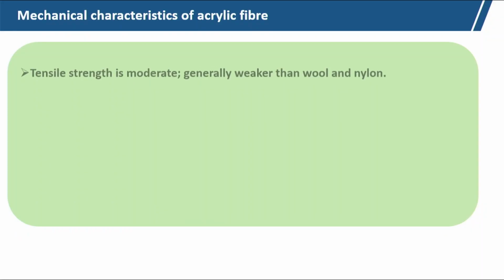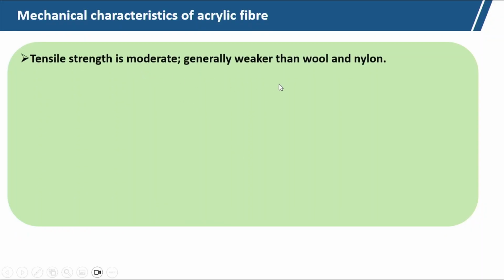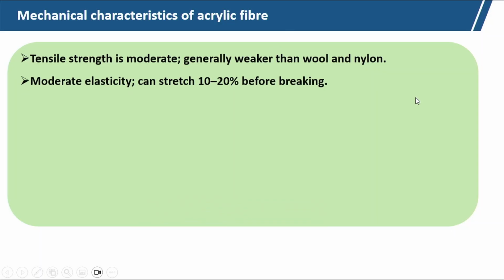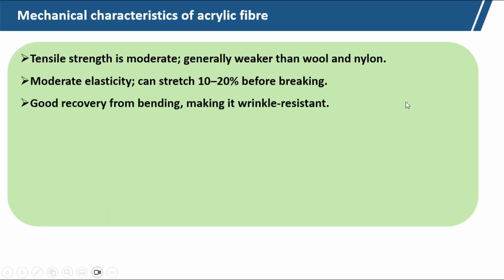So, mechanical characteristics: you can see its tensile strength is moderate, it is weaker than wool and nylon. Moderate elasticity, 10 to 20% breaking elongation. It has good recovery from bending, making it wrinkle resistant, and bending strength is very high. So, that is why we use this fiber in woolens, and it gets pilling. The presence of acrylic fiber creates pills in the woolens.